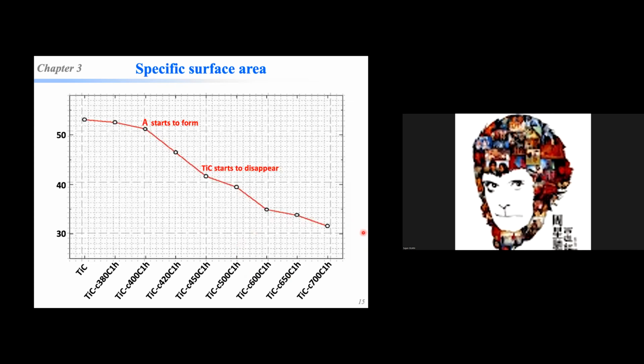And another one about the surface area. We also used the BET, and the result is something like this. Of course, after the oxidation and heat treatment in the carbon powder, there is also some decrease of the nanoparticle surface area. And when the anatase starts to form, it shows a sharp decrease. And then with the TiC disappearing, the decrease becomes a little slower. These two points are maybe interesting and important for the changes of the TiC and the forming of the TiC and TiO2 structures.